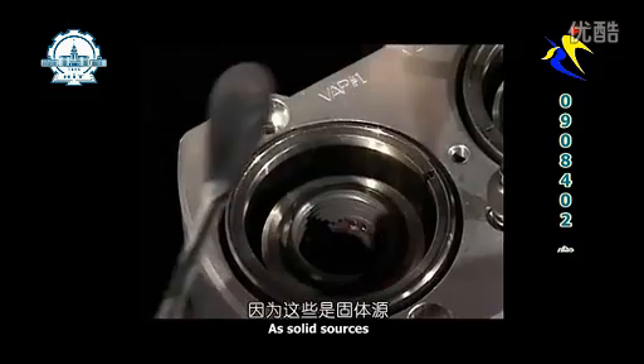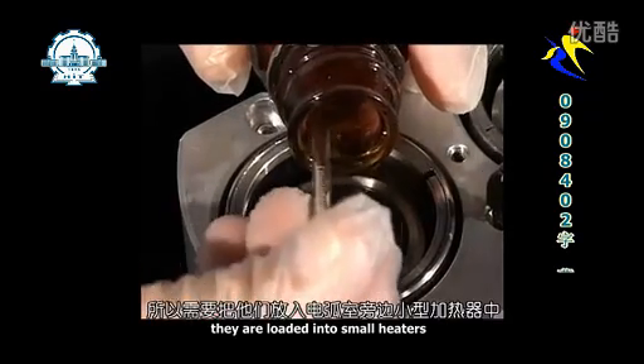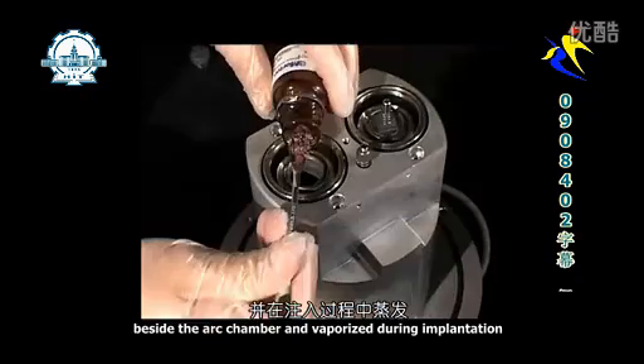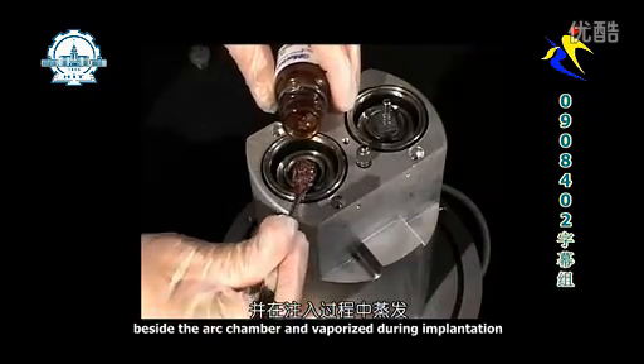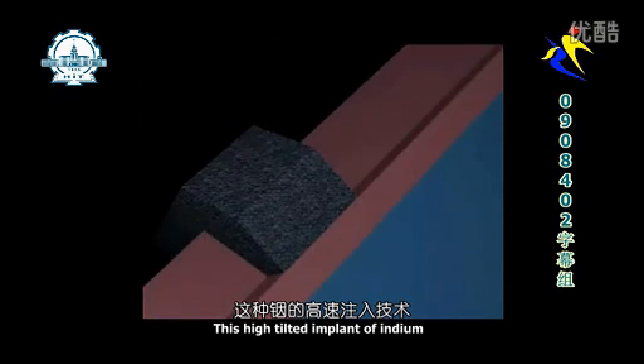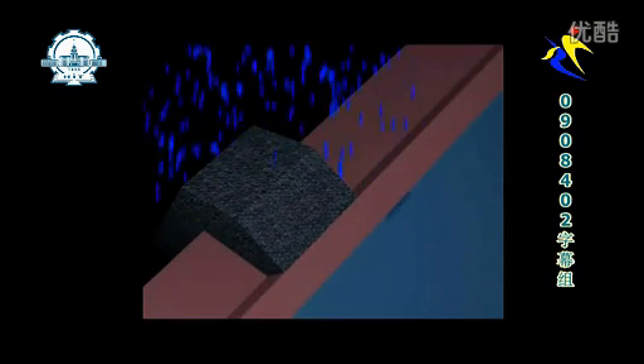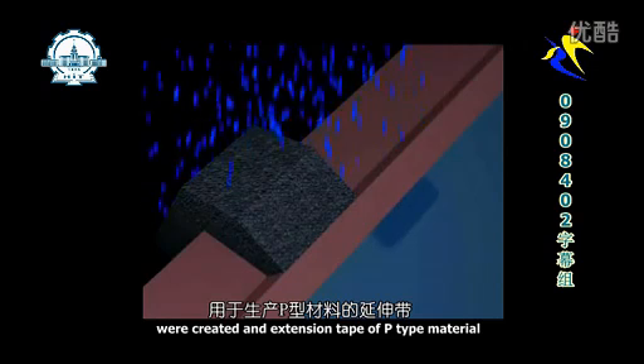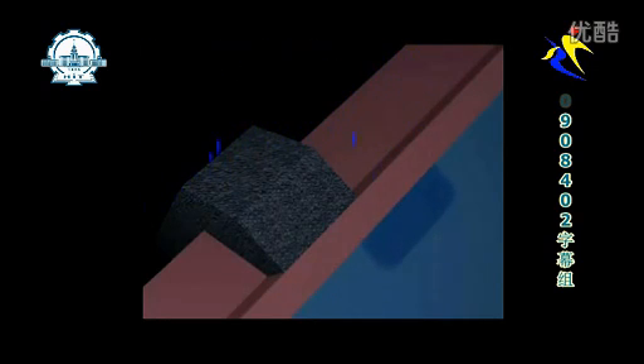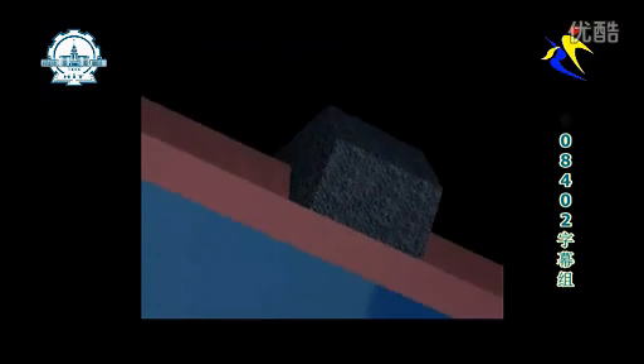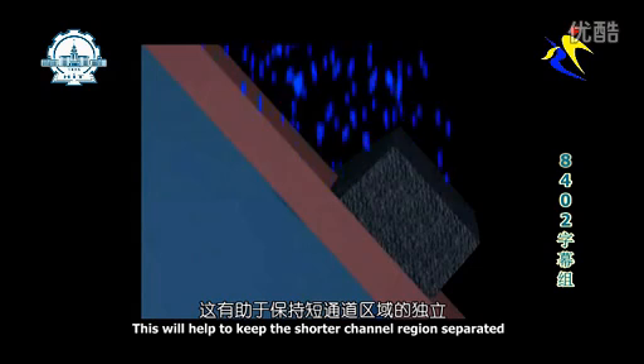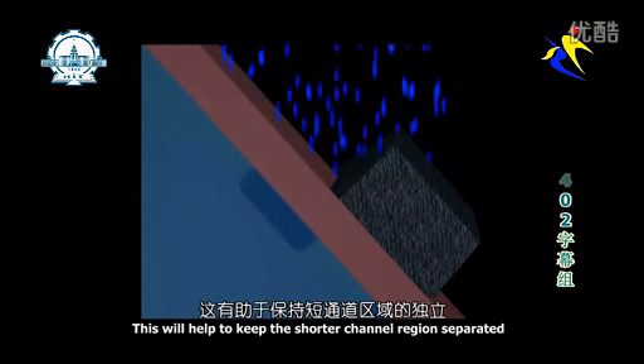As solid sources, they are loaded into small heaters beside the arc chamber and vaporized during implantation. This high-tilt implant of indium will create an extension tip of P-type material. This will help keep the shorter channel regions separated.